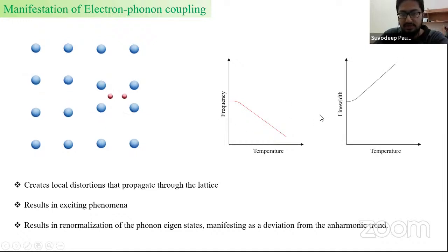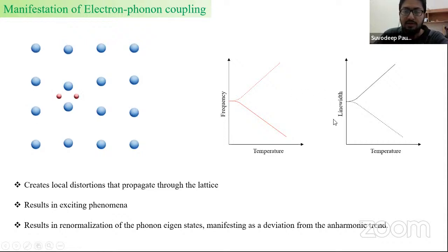So this is the frequency and line width of the phonon as expected from anharmonic behavior, and this deviation that we see represented by the dotted lines is what would happen under the influence of electron-phonon coupling.